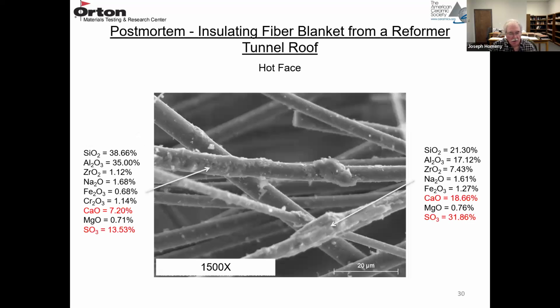So there are other areas that are even more contaminated. And I put down here in red what's really changing. So if you look at the areas of high contamination, it's a lime sulfur type material. So this is probably a calcium sulfate buildup on these fibers. You still have silica, alumina, and zirconia on both of these.